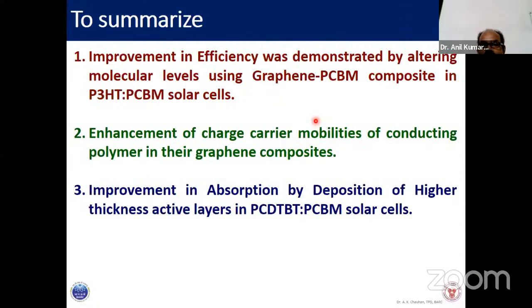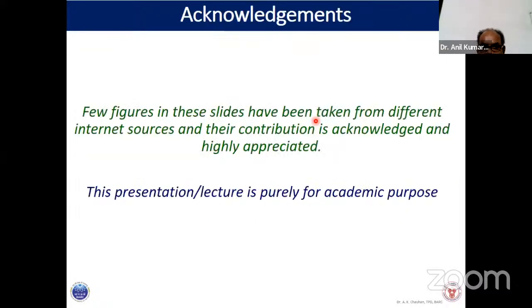In order to summarize, the improved efficiency was demonstrated by altering molecular levels using graphene PCBM composites in P3HT-PCBM solar cells, and enhancement of charge carrier mobilities of conducting polymers using graphene composites, and improvement in the absorption by deposition of higher thickness active layers in PCDTBT:PCBM solar cells, and then by solvent annealing, homogenizing these layers.